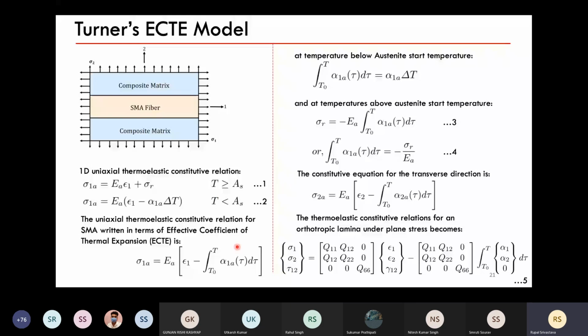So we have a value for our recovery stress, and taking sigma R, here we get a given value for our alpha from this. Whenever we do it experimentally, we are able to figure out sigma R. There's a method: we just attach our wire to a load cell, and then we heat it, and we get the values of load at different temperatures. So we are able to get sigma R at various temperatures, and we are also able to get E at various temperatures because there are temperature controlled UTM machines available. So we are able to get Young's modulus at different temperatures, and that is how we figure out what the alpha would be. We have the cumtrapz function in MATLAB, so we just calculate the cumulative alpha for each and every temperature.